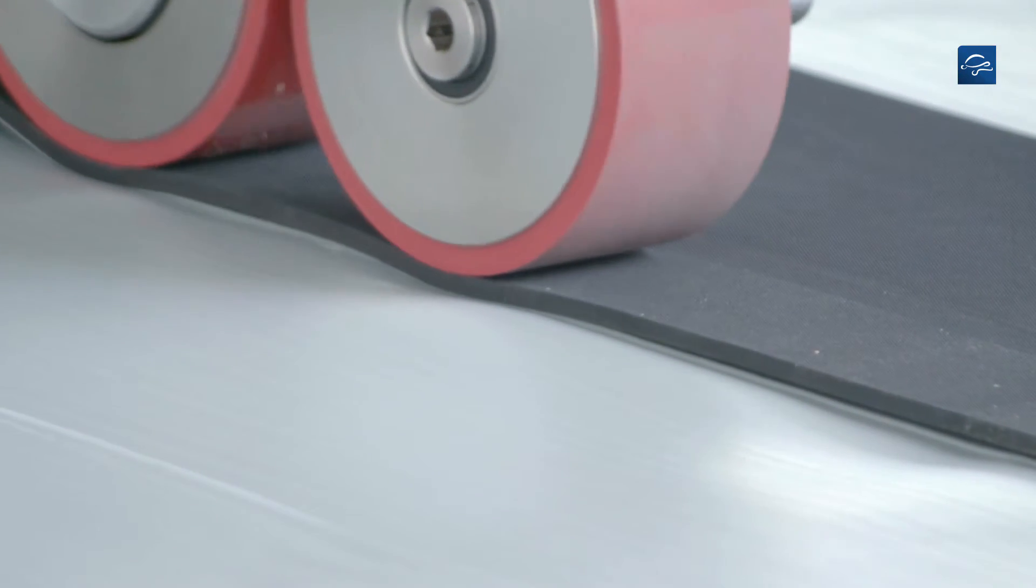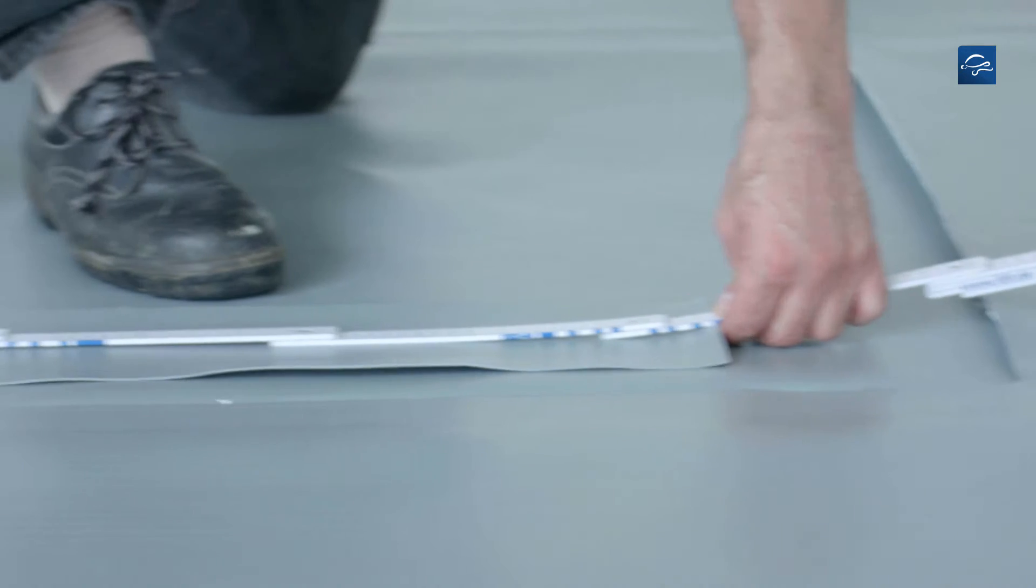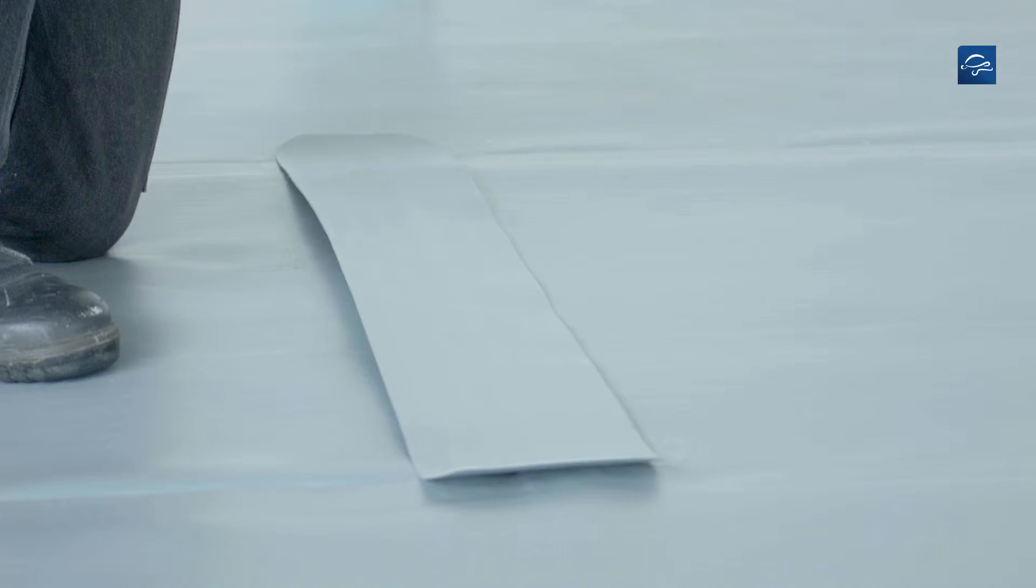With Rhepanol FK Roofing Membranes with welding edge for sealing the cross-joint, a 15 cm wide strip of weldable Rhepanol F is welded onto the seam area. The strip overlap at both ends must be at least 5 cm.